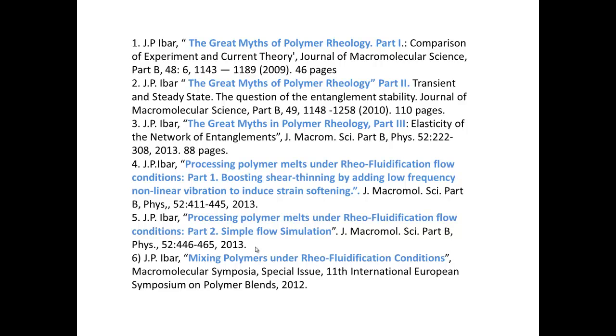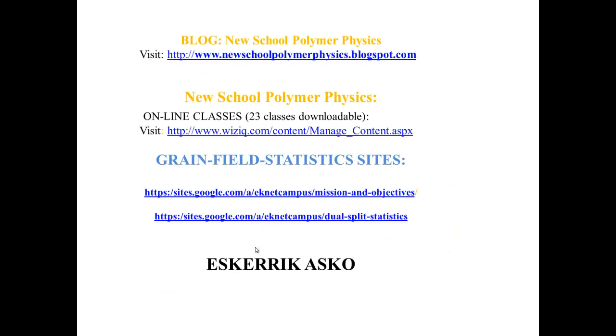Since I'm contending that I can do that with a homopolymer, I can indeed obviously try to do that and modify it and create a fantastic interpenetration for PET and polycarbonate, for instance, which I've done, or different molecular weights to create a polydisperse curve of a known characteristic, which is beyond what chemistry can do, by blending different molecular weight monodispersed and obtaining an interpenetrating network with a homogeneous stable entanglement network with a molecular weight distribution of known or desired characteristics. It goes on and on.